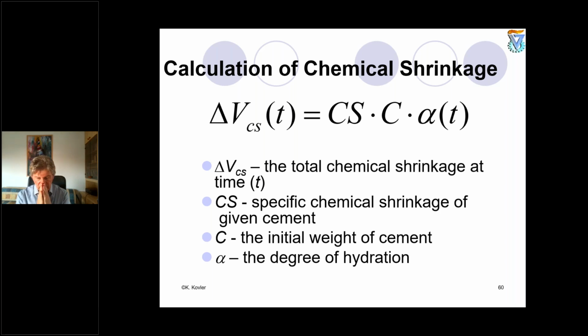A very important issue is to calculate accurately the chemical shrinkage to be compensated. If we successfully compensate chemical shrinkage, no autogenous shrinkage is expected. How to do it? This is the total chemical shrinkage at time t. CS means chemical shrinkage. CS here is the specific chemical shrinkage of the given cement. So this is a property of the certain cement.